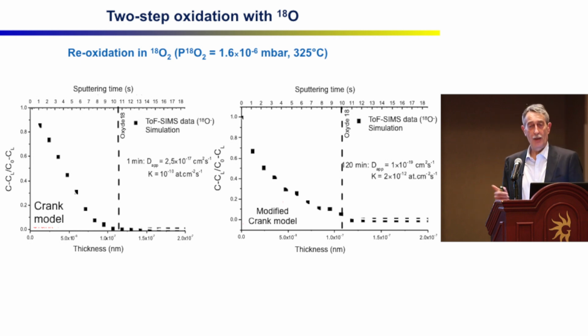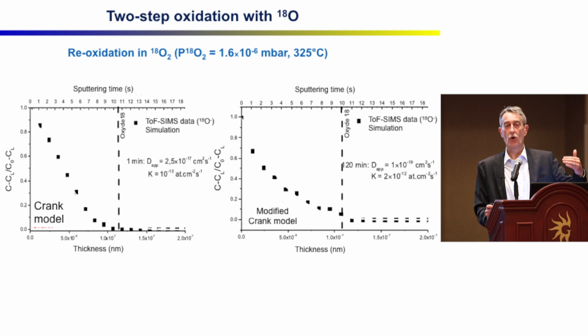So we did measurements like that after different oxidation times in water. And if we look here, which is for longer exposure time, we find a different value. In the first case, we find a value of the order of 10 to minus 17 centimeters squared per second, but in the other case, we found 10 to minus 19. And we checked this data. So what's going on? At the beginning, we start to form chromium oxide. And we know that from both the XPS and the ToF-SIMS. But with oxidation time, we then start to transform the chromium oxide into the nickel chromite spinel, NiCr2O4. And the diffusion coefficient is not the same.